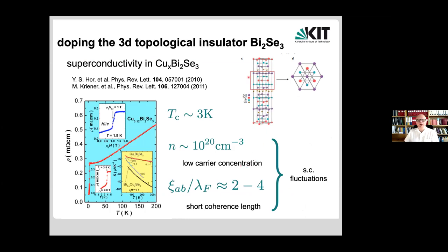by looking at doped bismuth selenide, a doped topological insulator that was found about 10 years ago to superconduct at around 3 Kelvin, with the interesting aspect that it does so at a comparatively low carrier concentration. And if you use the HC2 values and estimate the Fermi wavelengths from the quite well-known band structure, you find that they are of the same order.